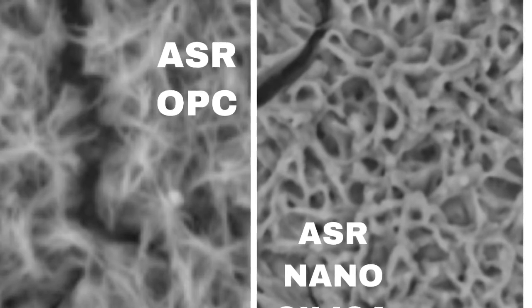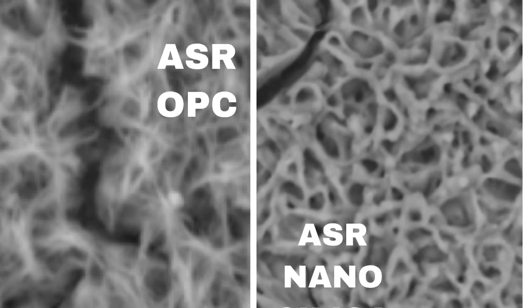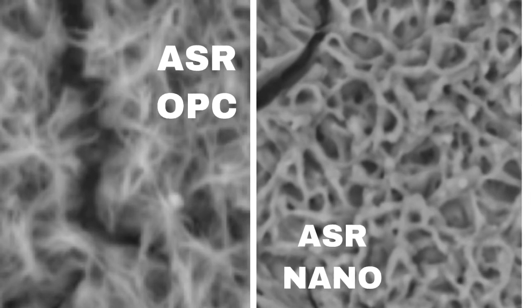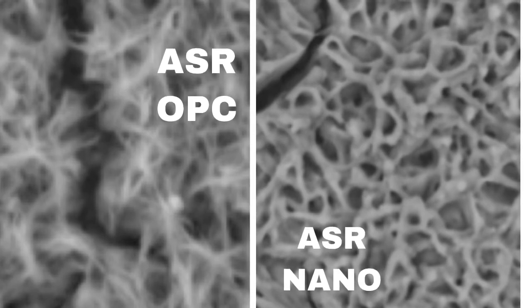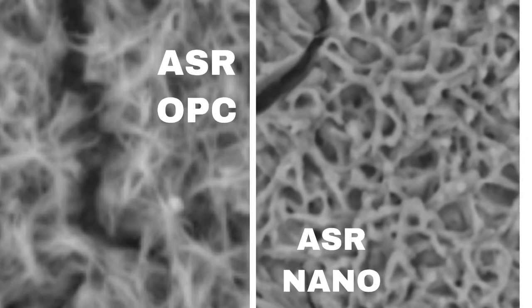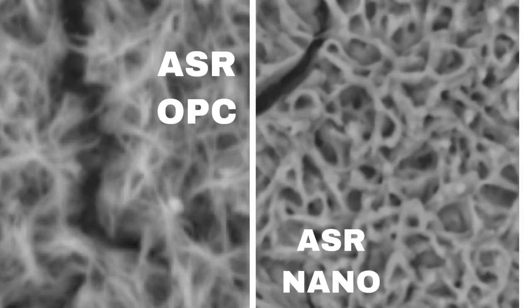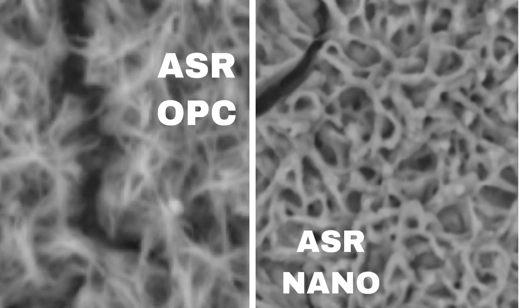That's what makes up the morphology of the normal ASR gel. It's part of those wispy wheat-like strands — it's very important that morphology, because it makes it possible for the water to continuously imbibe or be drawn into the ASR gel with those alkalis to keep the ASR gel thriving and surviving, going from immature to mature gel. When you look at the nanosilica sample, you see that the structure has changed — those wispy fibers creating smaller capillaries are gone. It's almost like there's a generic or arbitrary opening throughout the microstructure, and it's a larger opening than those wispy wheat-like fibers placed together.